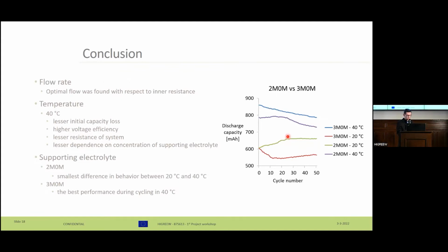So if I can draw some conclusions, we found the optimal flow rate with respect to resistance and pressure and energy losses. And with higher temperature, we found that the system has lesser initial capacity loss, a higher voltage efficiency, lesser resistance, and lesser dependence on concentration of supporting electrolyte. So if we want to cycle this battery at 20 degrees, the best combination of supporting electrolyte is 2MOM. But if we want to go to higher temperature, it looks like the 3MOM combination is the best.